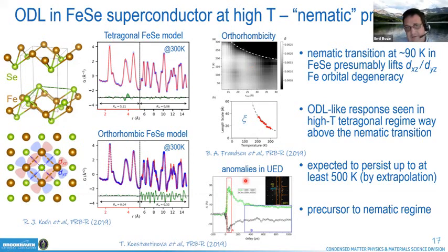And then interestingly enough, there were also ultrafast electron diffraction measurements, in which one thing that was anomalous that was observed at room temperature is that for early times upon excitation, there was an increase of certain intensities of Bragg peaks, which can only be understood as there being some kind of nanoscale disorder that is being regularized by the probe as compared to the negative time delays, which suggests that there is some kind of a precursor to the nematic regime at high temperatures in this system.